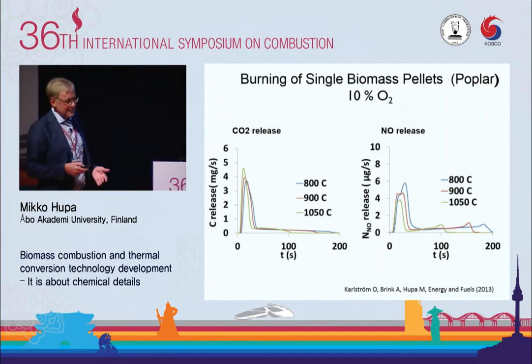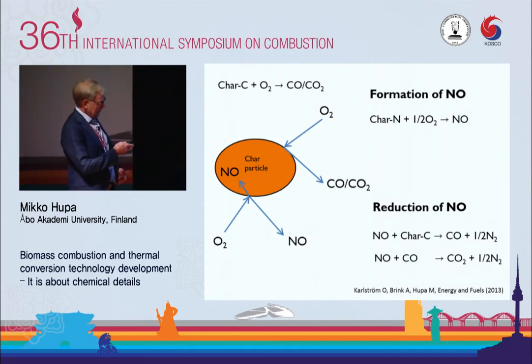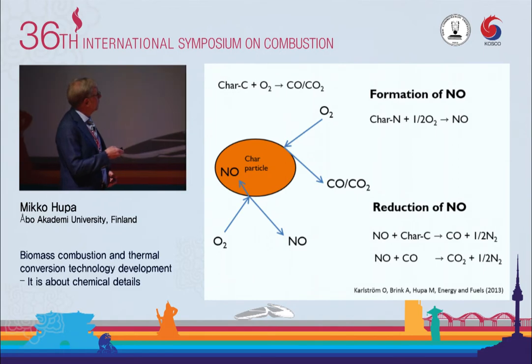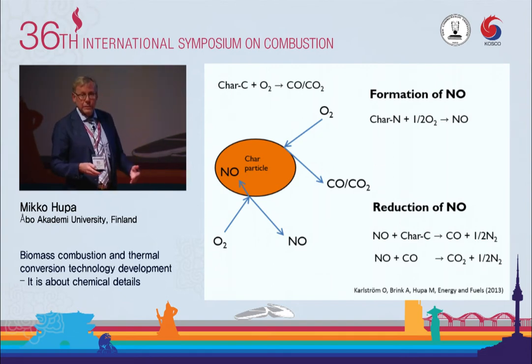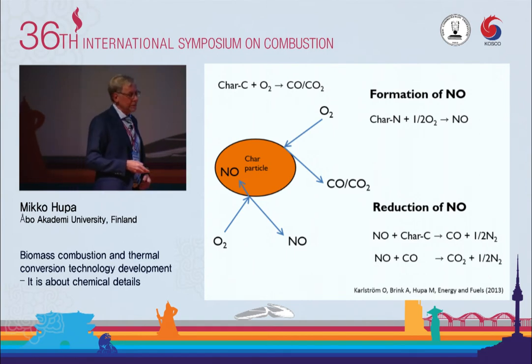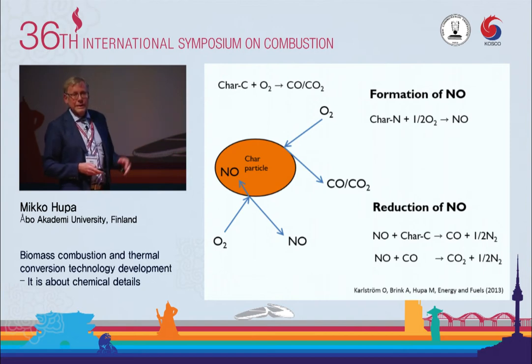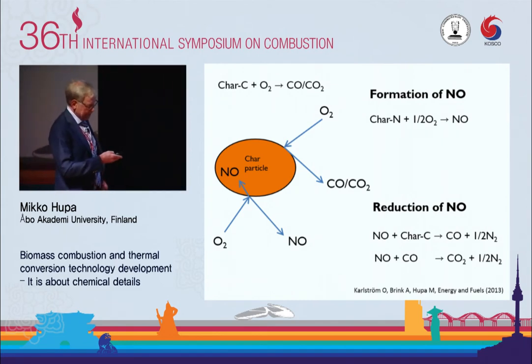The explanation here is that during char burning, we produce NO, which is a heterogeneous process. Part of the produced NO, of course, is diffusing away from the particle, but part of it can diffuse into the particle. And that is the key to this phenomenon. This ingoing NO will be reduced to N2 because of the active char. And here, again, the specific reactivity of the biomass chars gives the explanation. This you don't see with ordinary coals, but here the reaction goes this way.